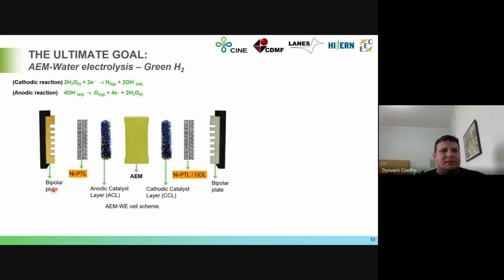The first one is the bipolar plate, which is followed by the porous transport layer. Here in alkaline medium, the porous transport layer is made from nickel. It is different from PEM, where it mainly uses titanium, which increases the price of the device a lot. So we have the anode catalyst layer, the core of the cell, which is the anion exchange membrane, then the cathode catalyst layer, the nickel porous transport layer. Here in the cathodic side, we can use just a gas diffusion layer based on carbon, for example, because this side of the device is negatively polarized, so it's not a huge problem. And the bipolar plate again.